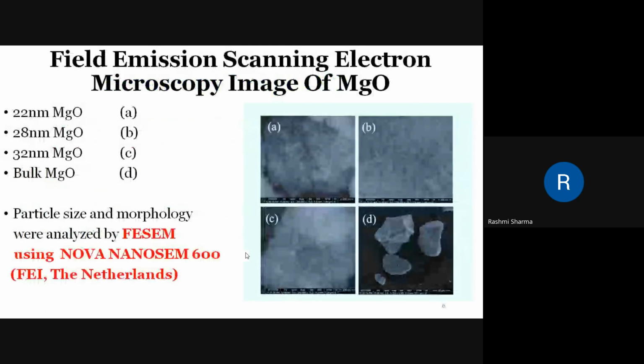So here is the FESEM image of magnesium oxide, where image A represents the 22 nanometer magnesium oxide, B represents the 28 nanometer magnesium oxide, C represents the 32 nanometer magnesium oxide, and D represents the bulk magnesium oxide. The particle size and morphology were analyzed by FESEM using NOVA NanoSEM 600.